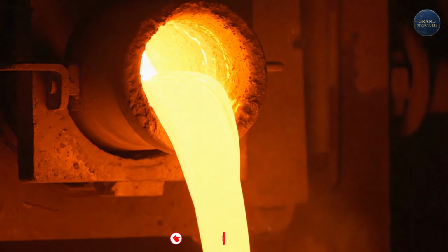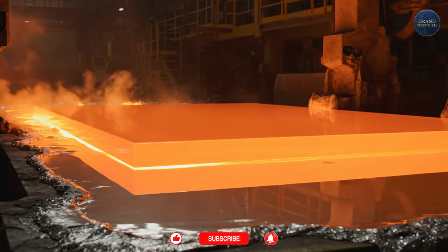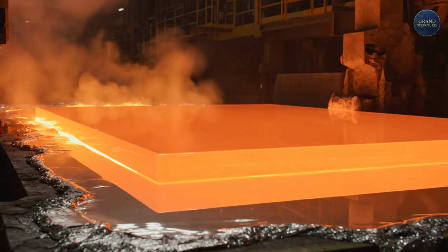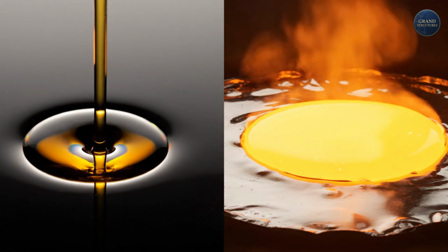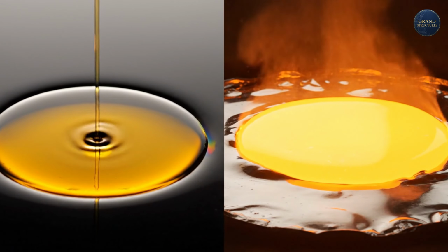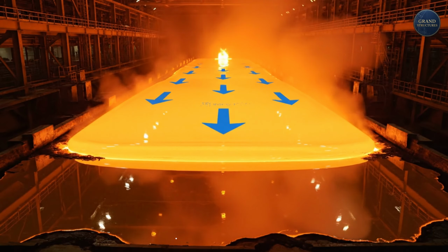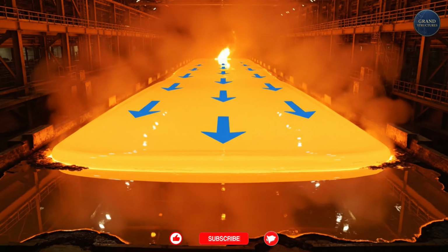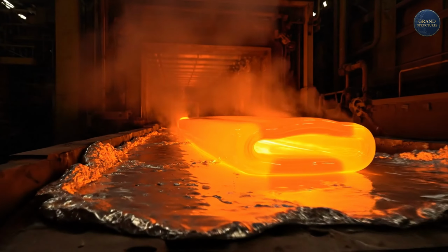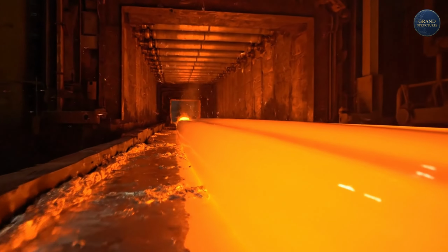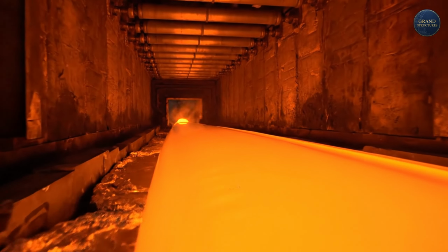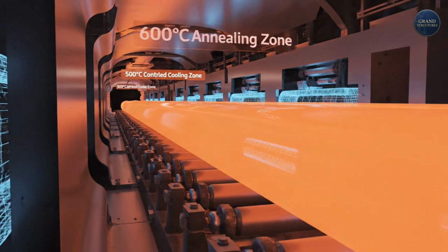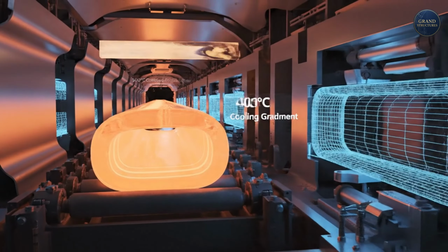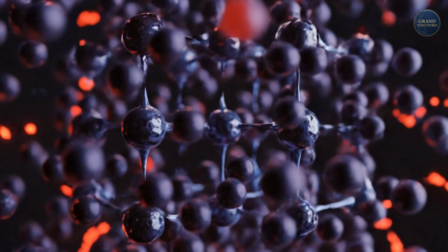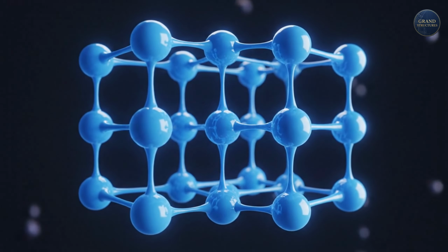The molten glass is poured from the furnace in a continuous, fiery ribbon onto a perfectly flat, perfectly shallow bath of molten tin. The glass is lighter than the tin, so it floats on top, just like oil on water. The molten tin is incredibly smooth, and gravity pulls the glass flat as it spreads across the surface. This river of glass, dozens of feet wide, slowly moves down the line, gradually cooling in a long tunnel called an annealing lehr. This controlled cooling process is critical. It removes internal stresses from the glass, preventing it from shattering. At the end of this process, we have a perfectly flat, perfectly clear, giant sheet of float glass.